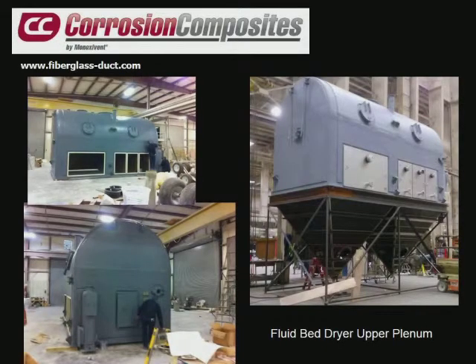Next, we're looking at a large upper plenum for a fluid bed dryer. We built this for a GEA corporation. And what it is, it's fiberglass laminate with a balsa core again. The core does two things in this case. It gives structure to that large piece of equipment, and it also insulates.